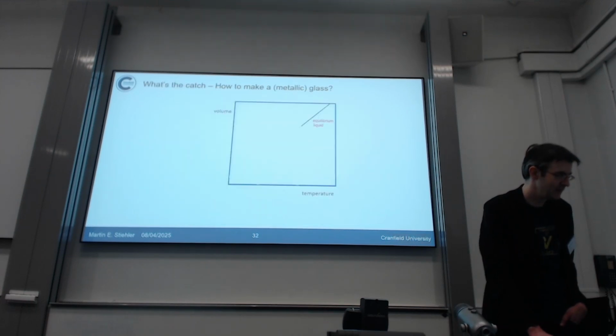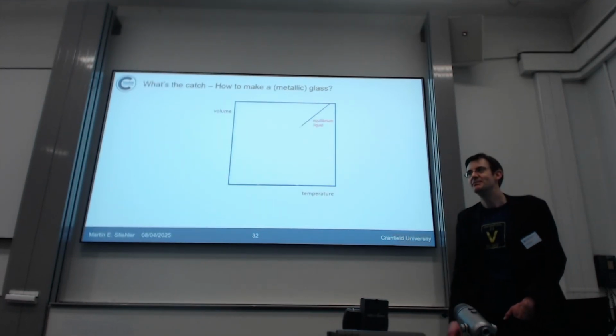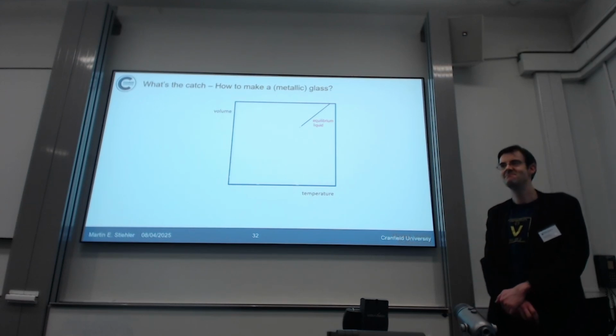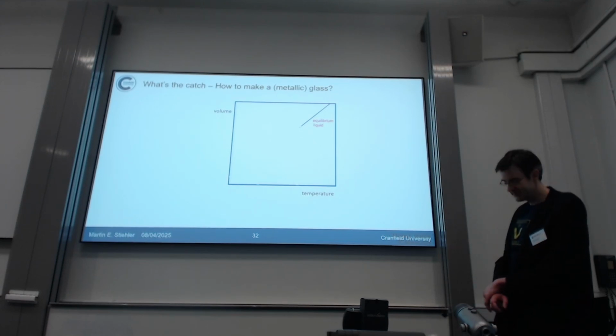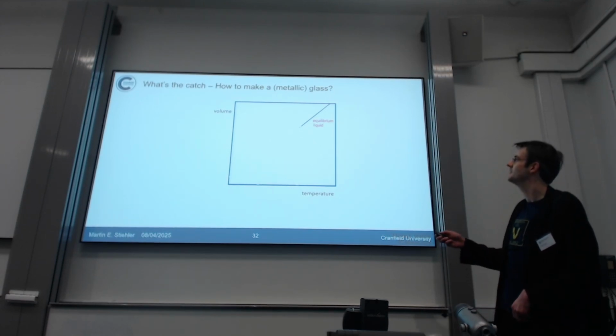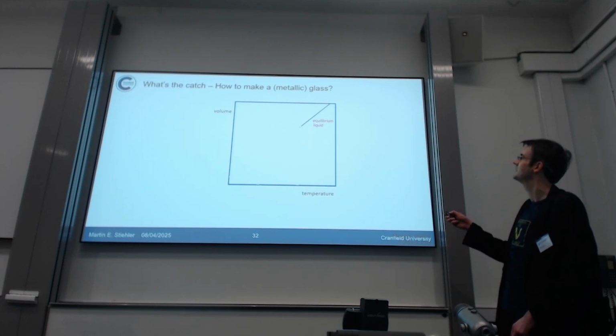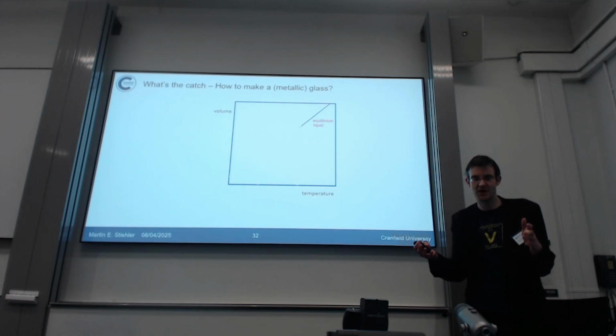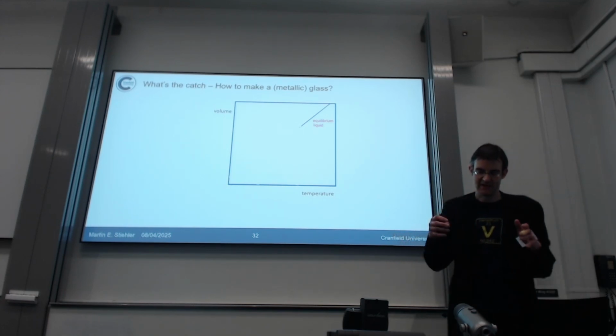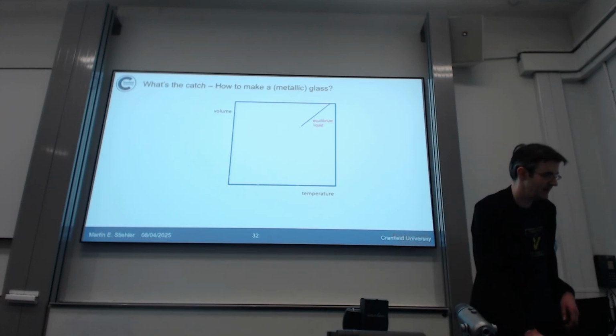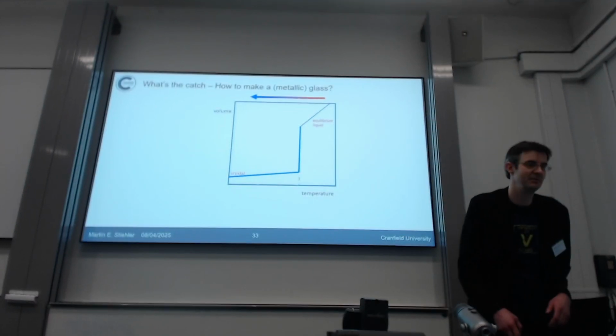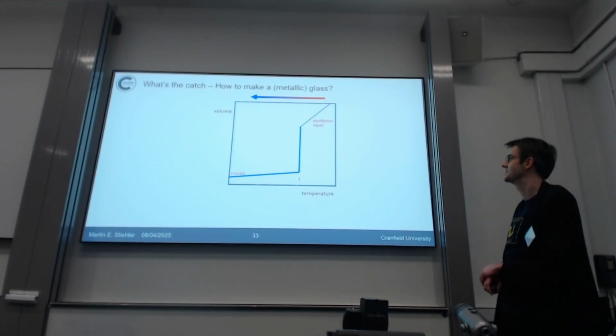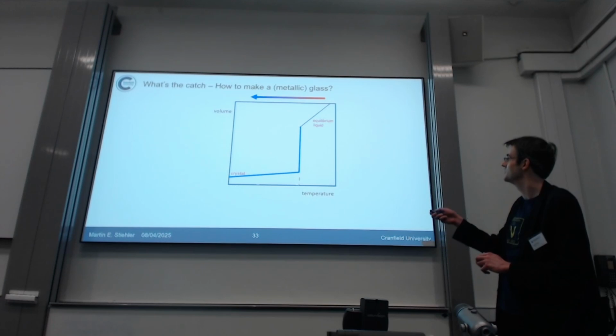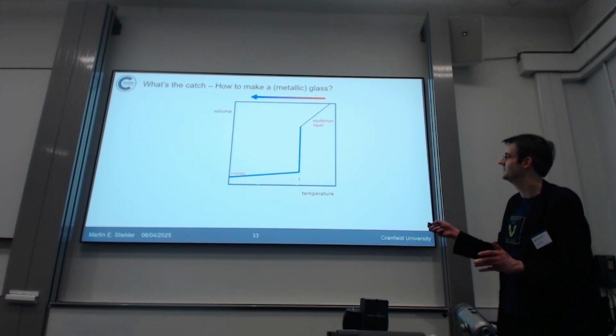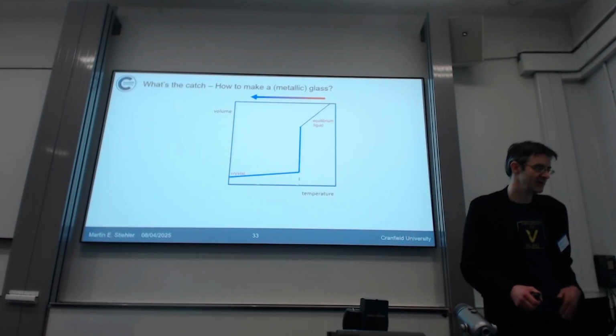And the problem is how you make these metallic glasses. You need to be very quick. Right, so this is a simple diagram just showing the volume over the temperature of a liquid at high temperatures, and you cool down the liquid. Like, imagine you do a casting process, you start at high temperatures, you cool it down, and you know that in the usual case at some point the material just solidifies, crystallizes, and has this high jump in density, and you have a crystal and you lose all the nice properties.